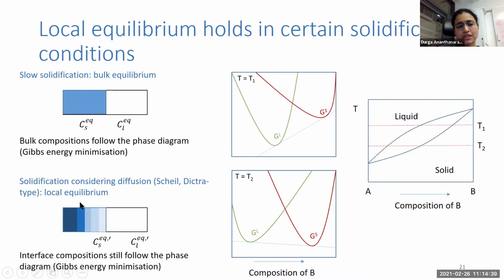But even here, we have this local equilibrium assumption at the interface, which means that every time you have a liquid of certain composition, the new solid that forms at the interface would still follow the phase diagram or the minimum Gibbs energy. So even though there is no diffusion inside the solid, at the interface this still holds. As the solidification proceeds, there will be a gradient in composition, so the segregation is still captured by this, but it still sticks to equilibrium at the interface. One more level of approximation would be a DICTRA type calculation, where we allow for diffusion in the solid and the liquid as well, but still maintain the local equilibrium at the interface.